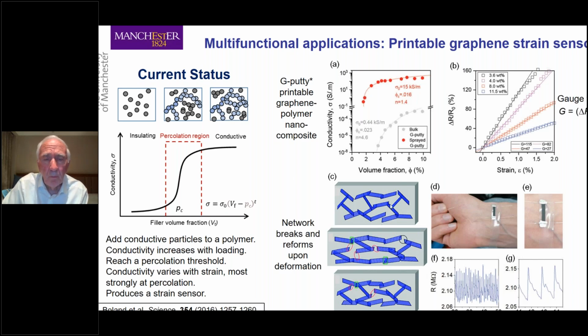Now, what the mechanism is essentially, as far as we're concerned, is that we have a percolated network to start off with. We then stretch it in the horizontal direction. You get breaks in the junction points, the resistance goes up, and of course, if you let it go, it all springs back. And I've just got one example here of where we've used this material, and this is by using a strain sensor to put on the wrist. You can use this graphene loaded putty paint or coating to put on a substrate, and then you put it on where the pulse is.